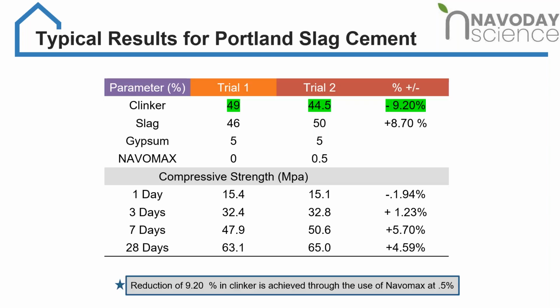So these are the typical results of Portland slag cement with and without Novomax used at 0.5%. You can see that we have increased the percentage of slag from 46 to 50. Normally, when you increase the slag by 4%, your one-day strength goes down by another 2 or 3 MPa. But with the use of Novomax, even though we are slightly lower at one day, it's very much comparable to the control. And if you look at the 28-day strength, we are around 4 to 5% higher than the control. Next slide, madam.